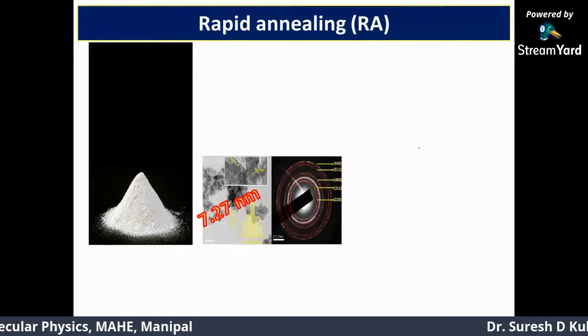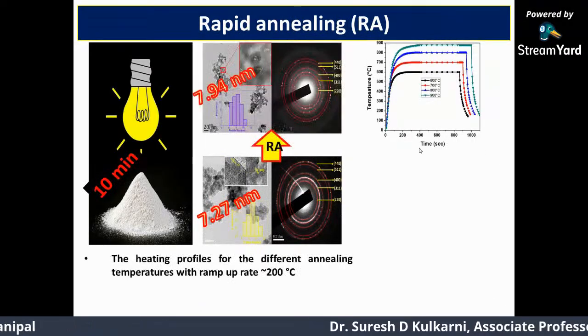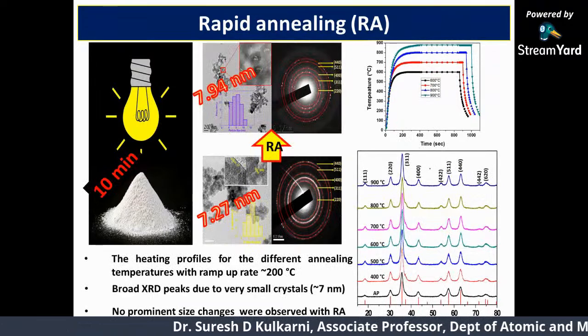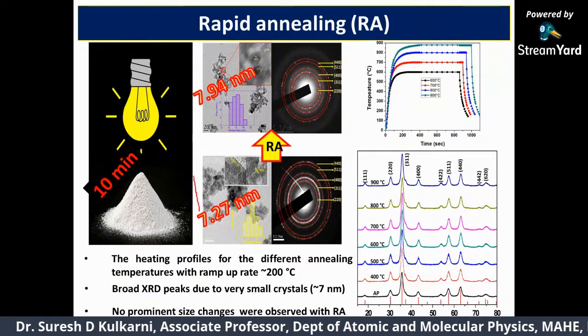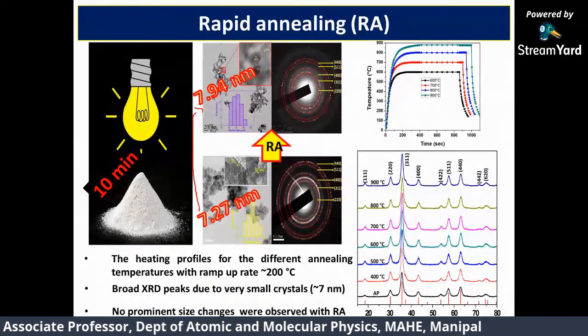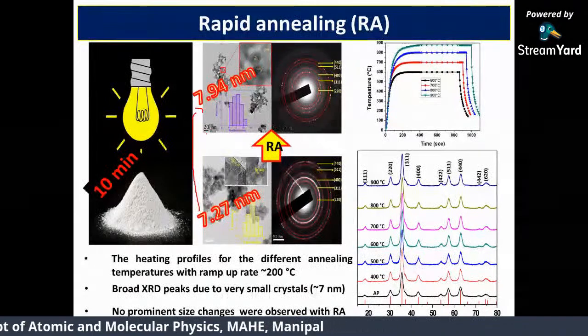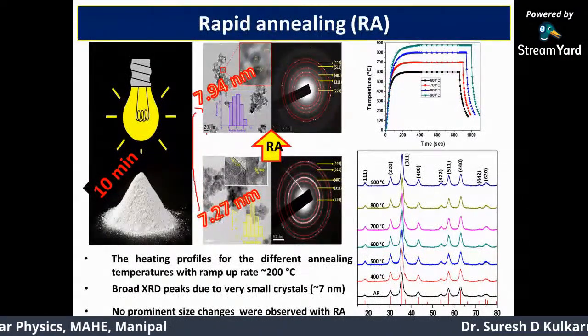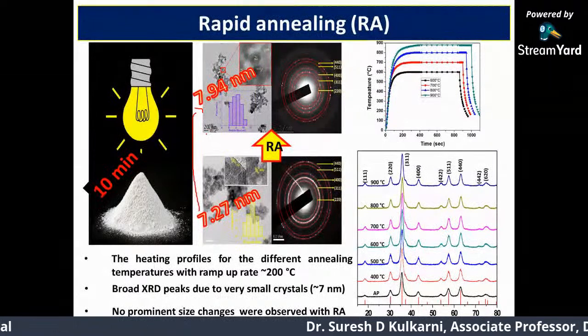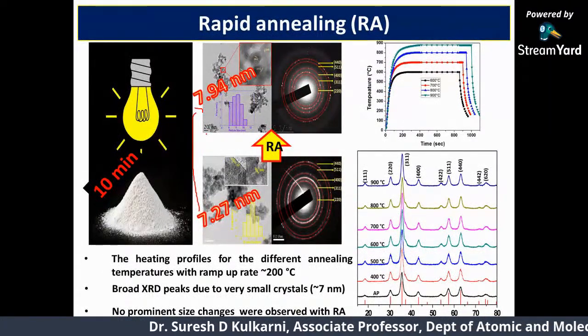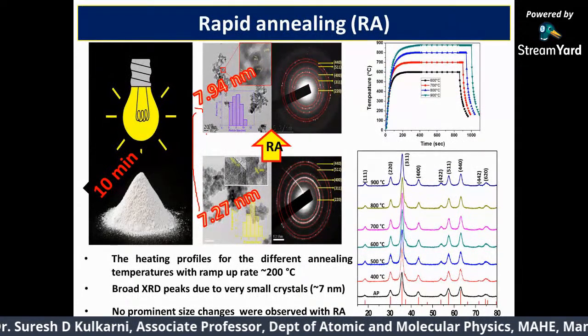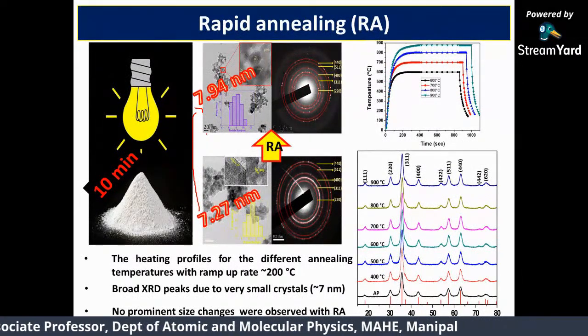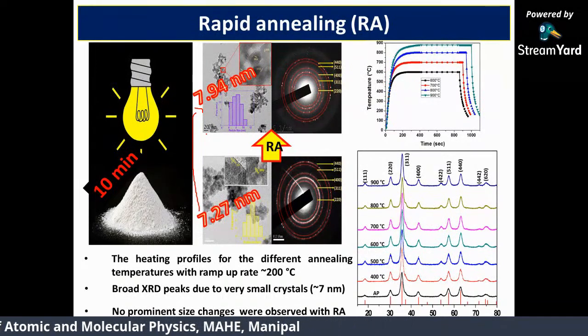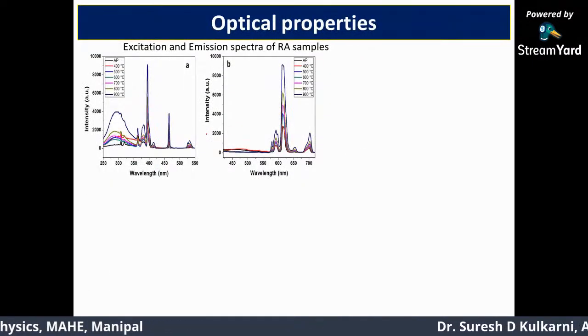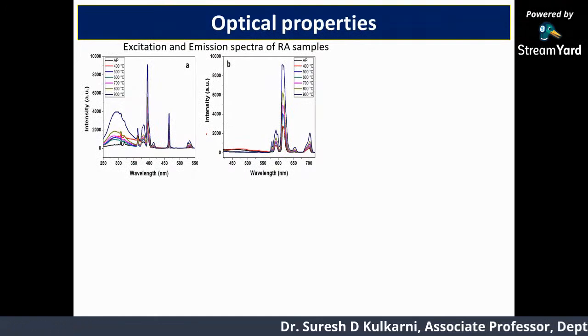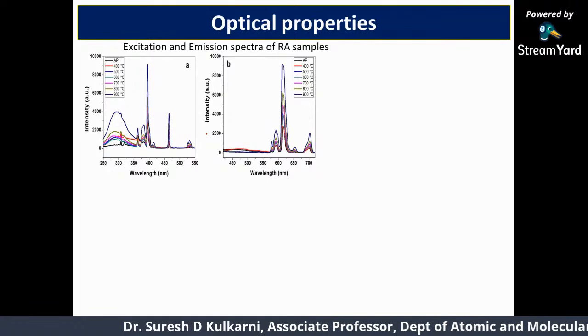And with the use of rapid annealing on the same powder, what we have done is we are showing you that there is no change in the crystallite size. You see, from 7 nanometer to only 8 nanometer. Generally, whenever these particles are heated under high temperature, the particle size grows. Say 7 nanometer may go to about 30, 40 nanometers. But here, when we have annealed using rapid annealing, a much faster annealing, we have seen that there is no change in the size. Okay, but having said that, there is no change in the size, but there is a remarkable change in the optical properties of the material.